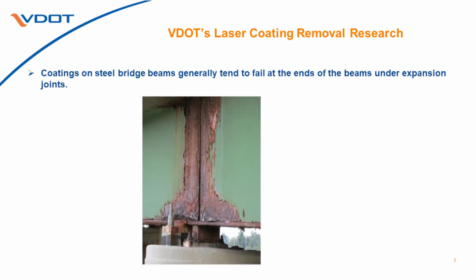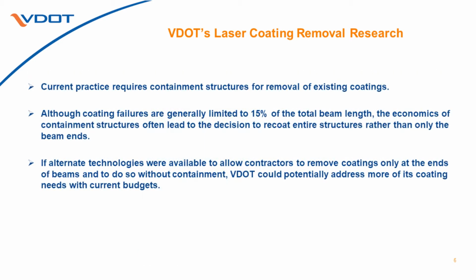Coatings on steel beams tend to fail at the ends of the beams under leaking expansion joints. I'm sure you've all got a picture like this somewhere. And so, of course, the current practice requires containment structures for removing existing coatings. Although coating failures may generally be limited to about 15% of the total beam lengths, the economics of constructing containment structures many times may lead to the decision to recoat the entire surface.